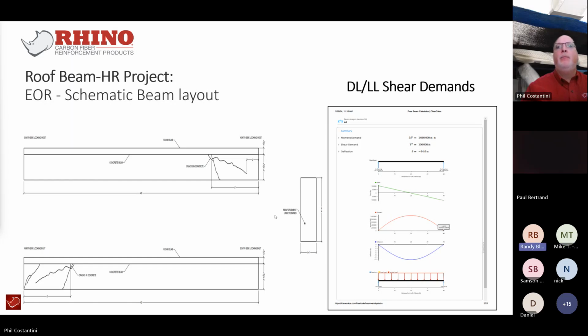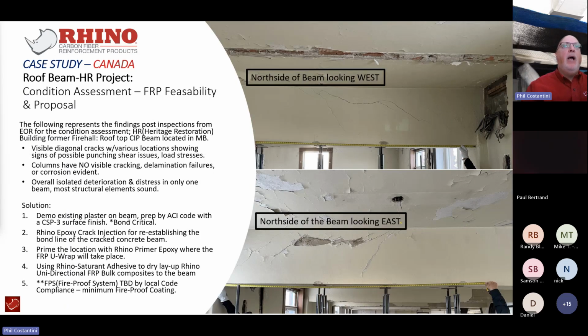You can inject them with epoxy, structural epoxy. Congratulations, you win. Exactly. So, demo the existing plaster on the beam, prep it with a CSP3, making it bond critical, and then epoxy crack inject to reestablish the bond line of the cracked concrete beam. Right? Fair?